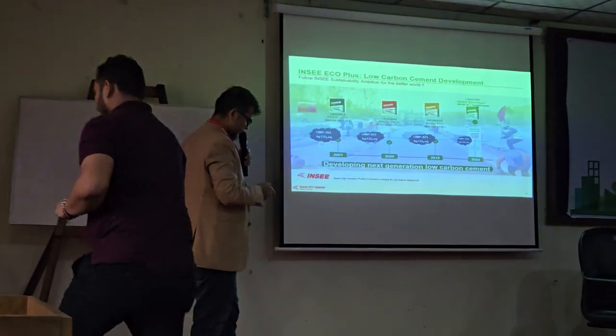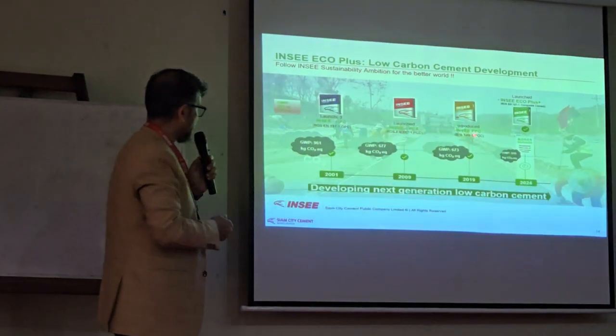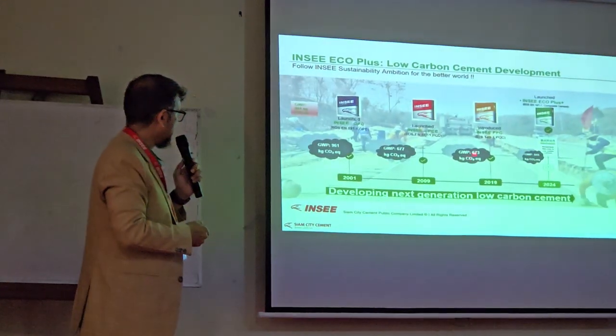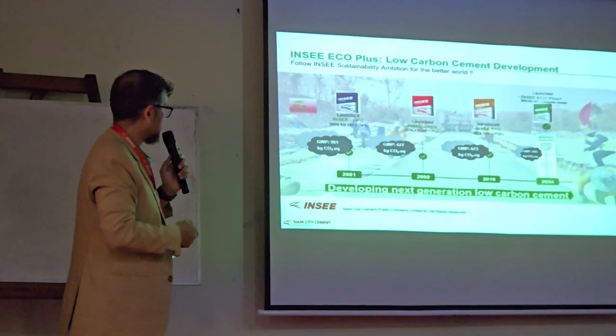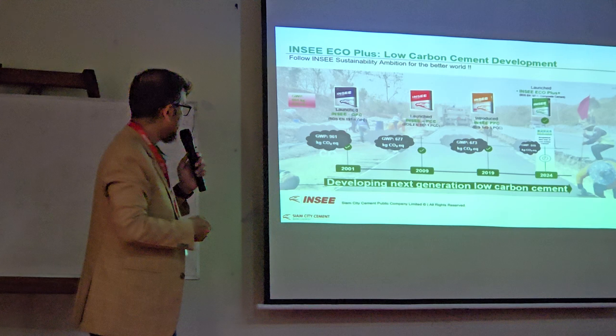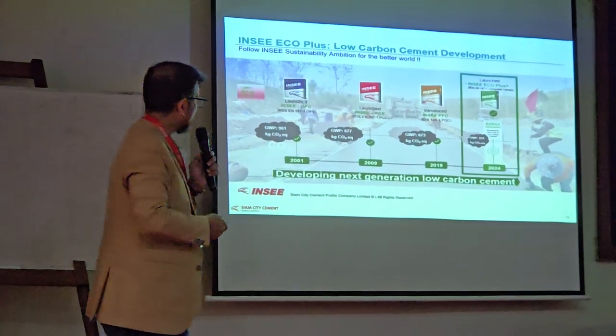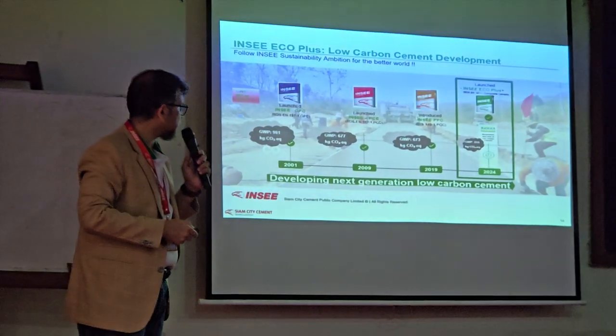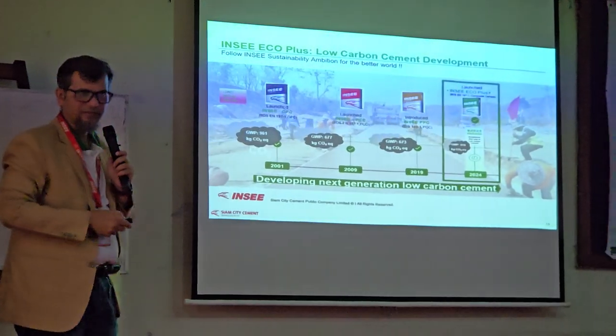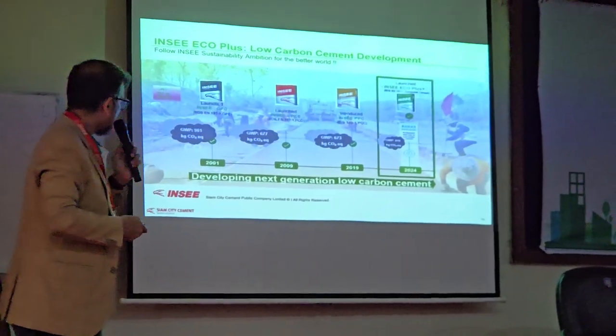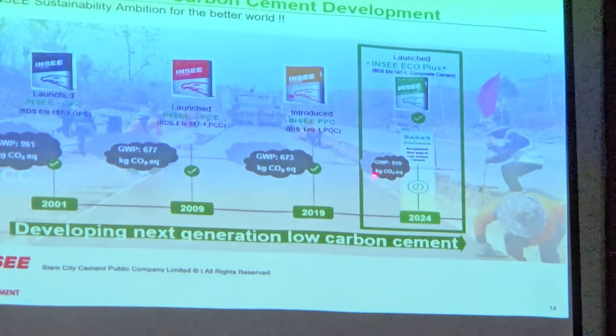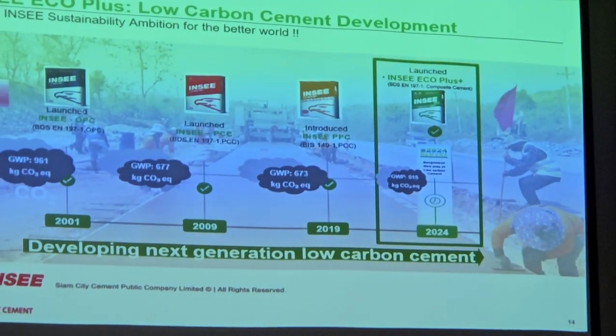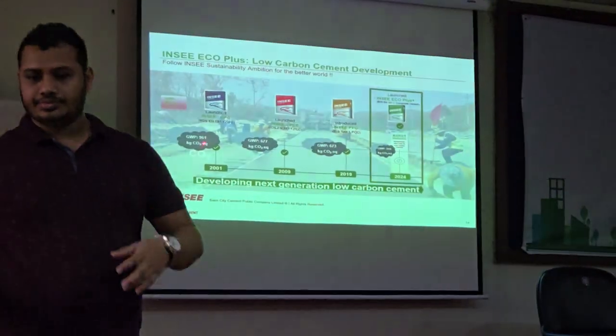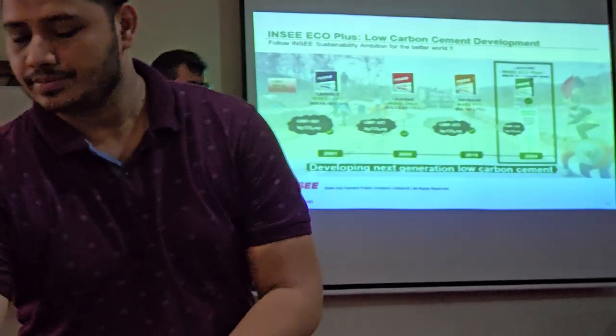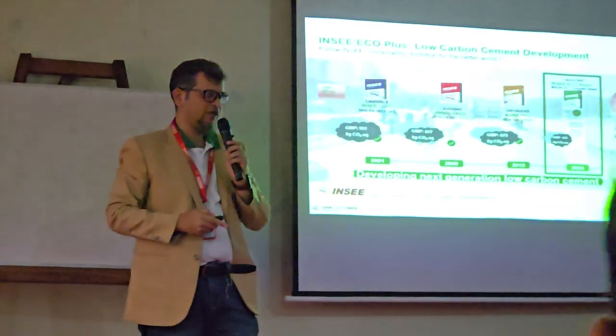And then if we make PPC, which is Portland Pozzolana cement, the carbon dioxide emission is 673. So these are still high. And surprisingly, we found that if we use EcoPlus, our brand name, and it's the same five category cement, it emits only 519 kg carbon dioxide. So from 961 to 519, we could almost halve the carbon dioxide emission to the environment.